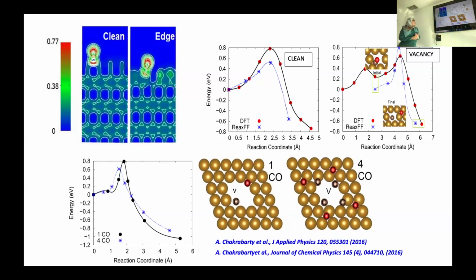So what we said is, okay, if we run molecular dynamics simulations, we should be able to capture the main phenomena that are happening. So we looked at the reaction coordinates. This was for the presence of one CO molecule, but in reality, we know that the surface is covered with several CO molecules, right? It's very unlikely that the surface has only a few molecules on it. So we included 4 CO molecules in this case.